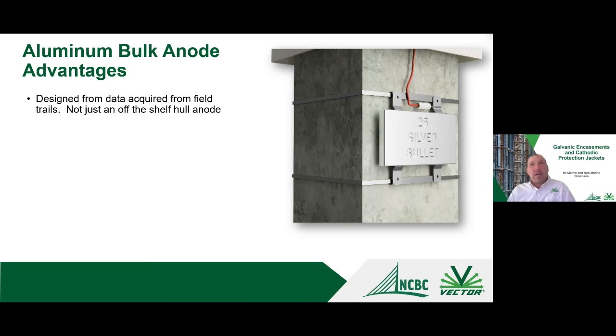Again, the aluminum anode was designed from data that was acquired from the field. The anode was sized for it, put in, and then the appropriate size anode was made. Like I mentioned, 25 pounds seems to fit about 90% of the piles. When I say it fits about 90% of the piles that are typically being jacketed out there, that leaves another 10% of jackets on piles where it wouldn't.